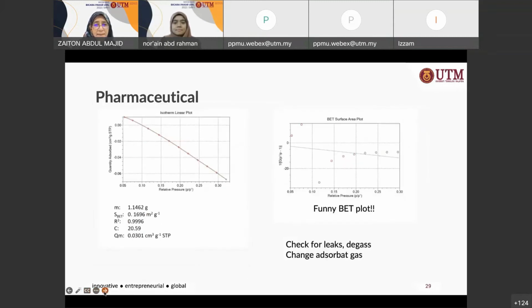And then another example. I like this example actually, for a pharmaceutical. Notice that when you increase the pressure, the uptake decreases drastically. This is totally not right. A very funny isotherm. And if you look at the BET plot, between 0.05 to 0.3, it doesn't resemble any of the BET transformation plots that we expect. No linear range whatsoever. You look at only between 0.1 up to maybe 0.15, and then the rest is very funny. So again, here check for leaks, degassing, check the adsorbed gas.